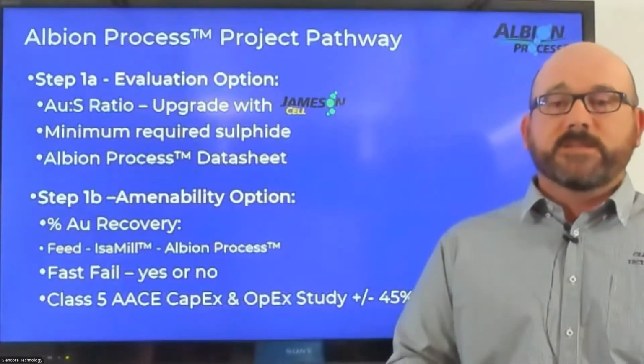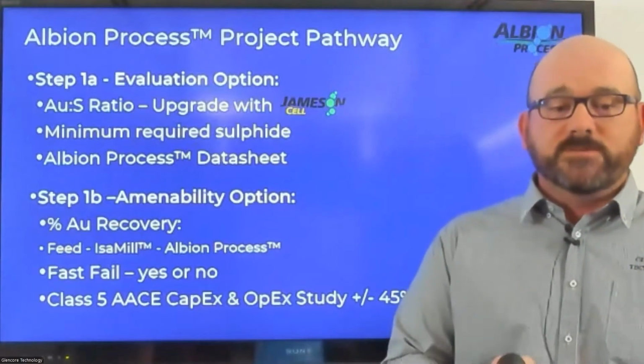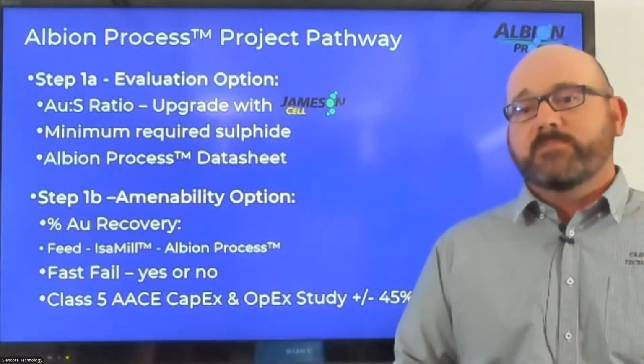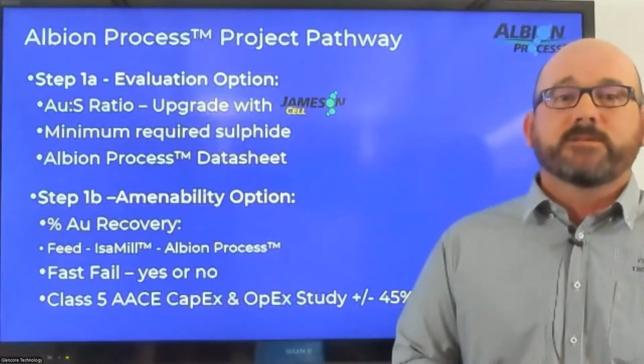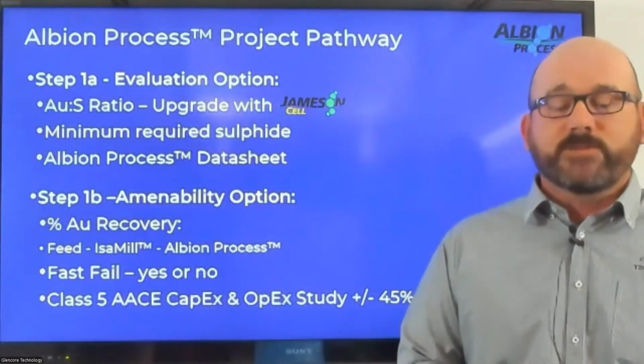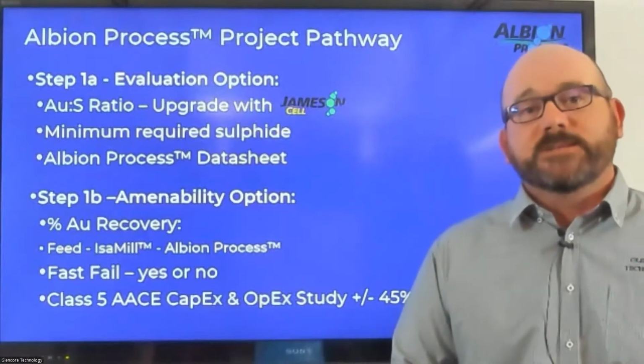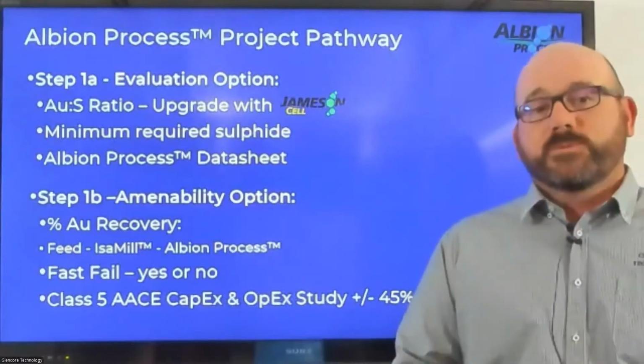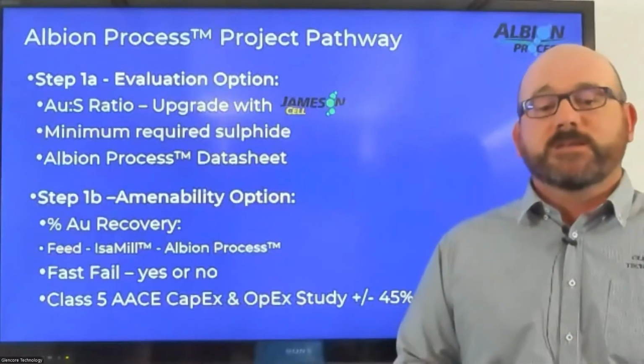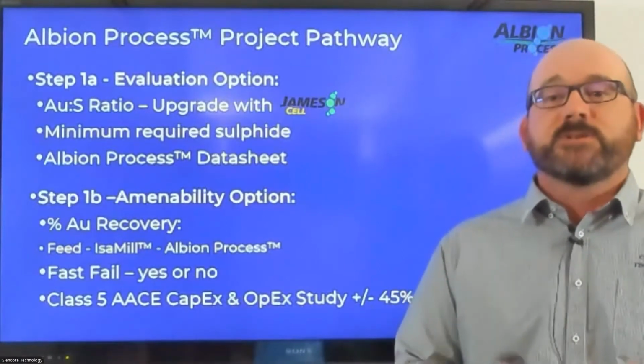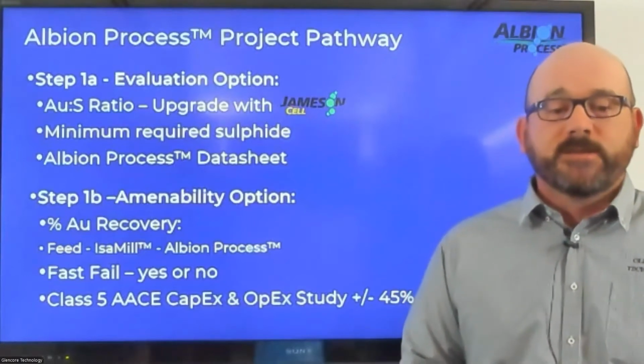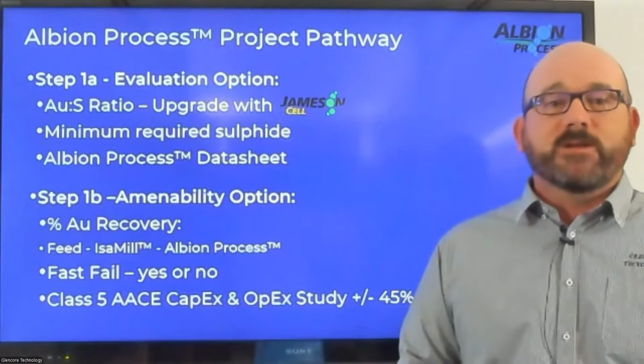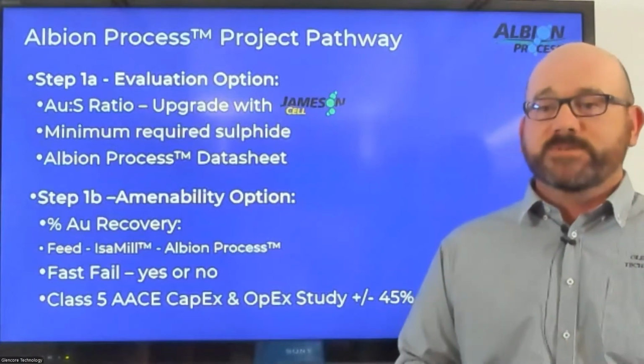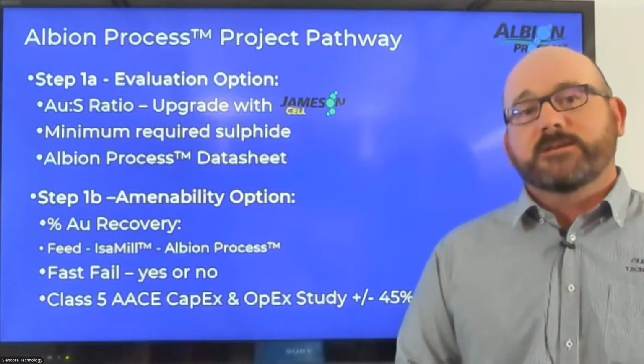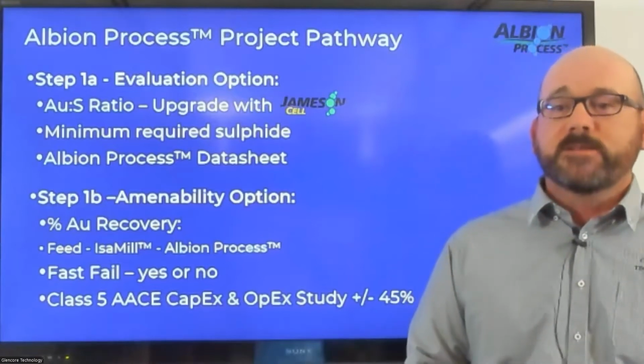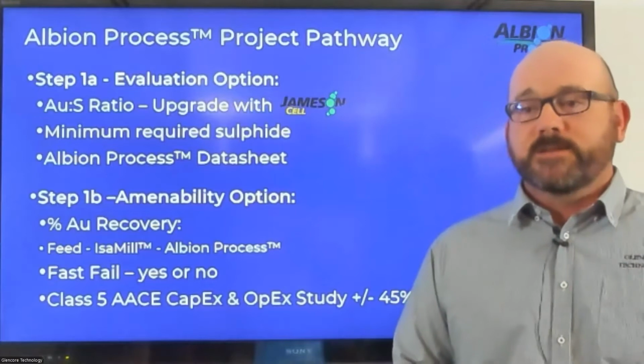If the gold to sulfide ratio is really low, then perhaps there's an opportunity to upgrade the concentrate using flotation. Glencore Technology has the Jameson Cell, which has great efficiency at flotation to do this, and can supply either single cells or a full concentrator. For the Albion process, we're looking at a minimum of 10% sulfide. This allows the oxidative leach to run autothermally,